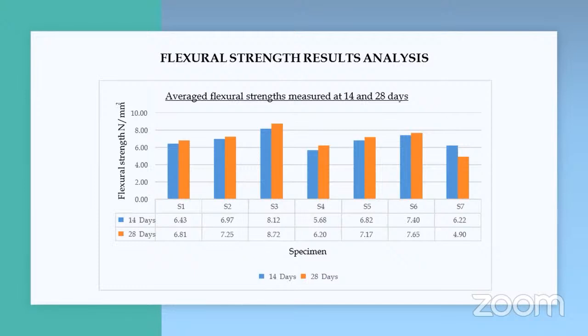When the PVA content was gradually increased up to 1%, look at S3 and S6: the flexural strength of cement mortar had increased due to the binding effect of PVA. However, if the PVA content is further increased up to 3%, look at specimens S4 and S7, it may act as a protective coating for cement and RHA particles and reduce the formation of calcium silicate hydrate during the hydration reaction.